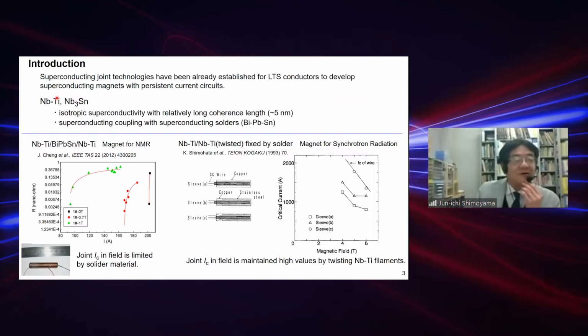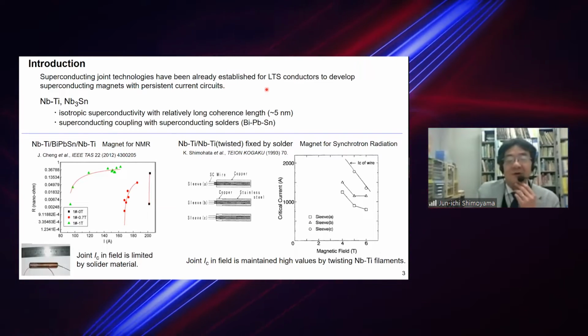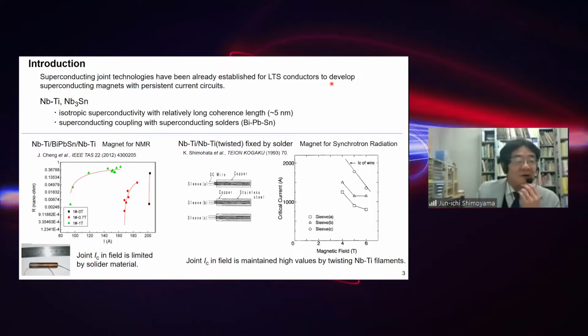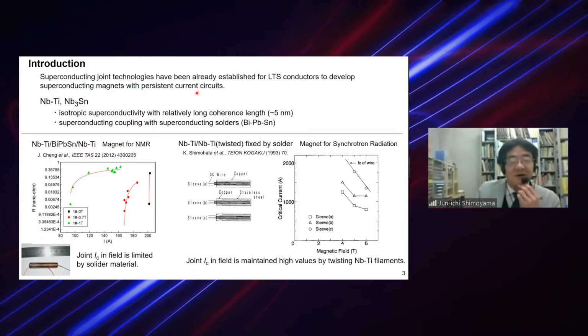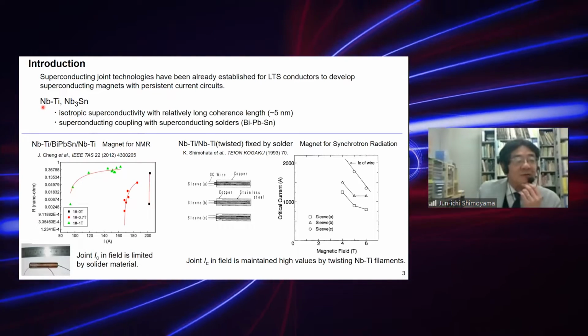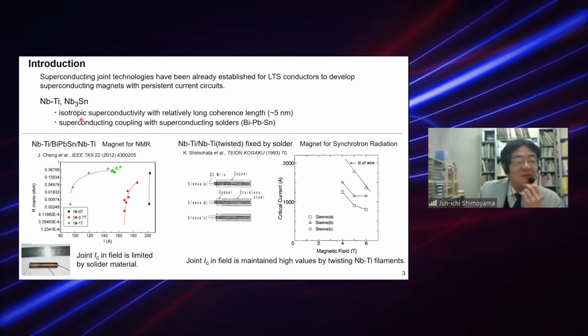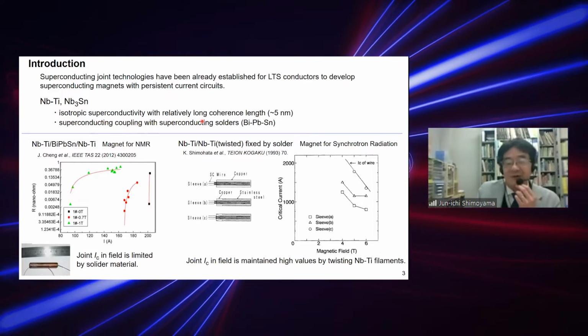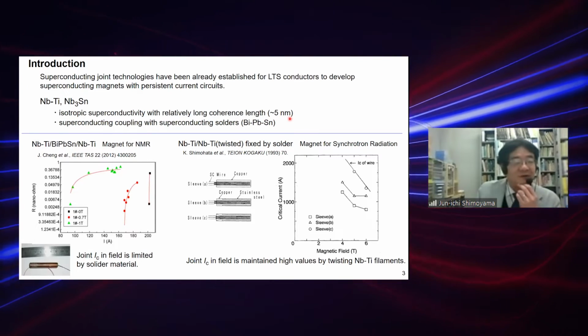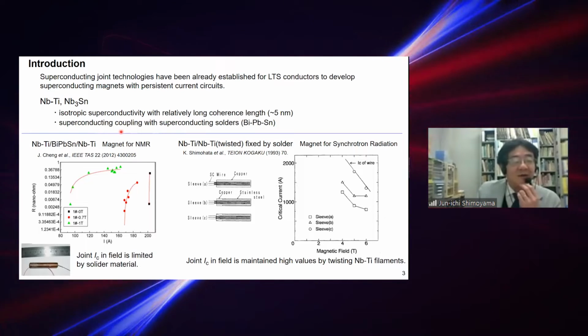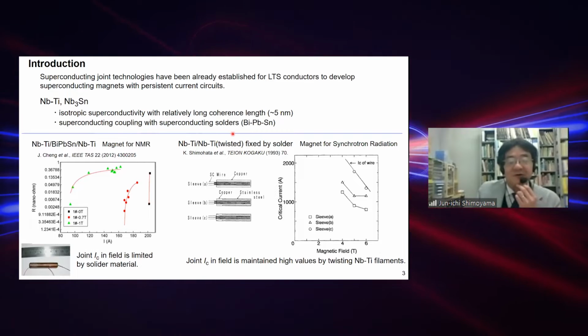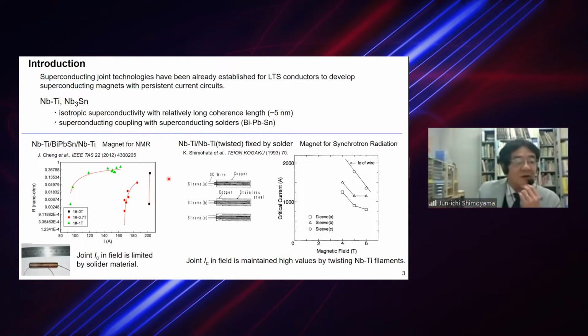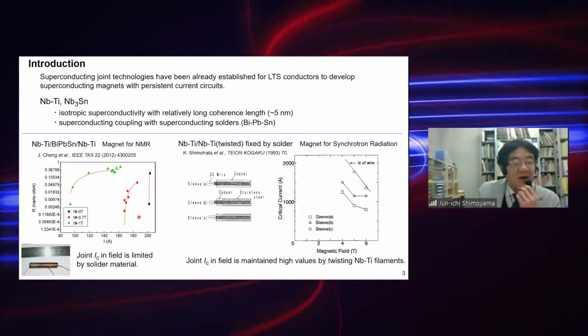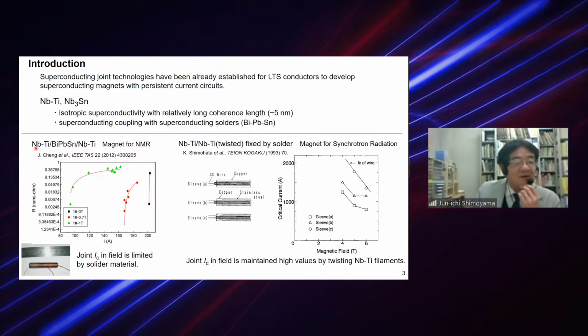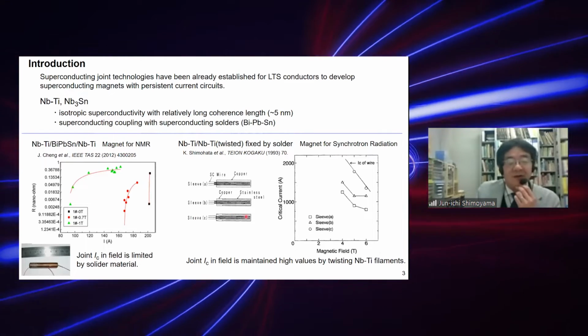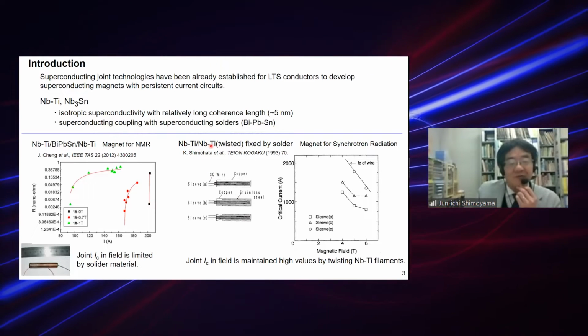So most of you know that superconducting joint technology has been already well established for low temperature superconductors to develop superconducting magnets with persistent current circuits. For example, niobium-tin, Nb3Sn, and niobium-titanium are isotropic superconductors with relatively long coherence lengths, approximately 5 nanometers. And superconducting coupling can be made with superconducting solders using such as bismuth, lead, and tin. As you see here, you can see a very nice superconducting joint between niobium titanium wires via solder. But in this case, also niobium titanium wires were twisted in the solder.